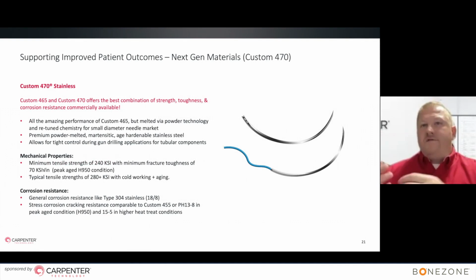So we talked about 465, and many of you may not be aware that there's a sub-variant of this alloy called Custom 470. This alloy provides very similar characteristics. It's a standard blend of Custom 465, but it maximizes toughness, minimizes grain size, and enhances machinability by providing this product in a powder-born process. So in other words, this is born as a powder and we consolidate that into the wrought form. We did tweak the chemistry slightly, and we produced that product through the powder melt technology, as I mentioned, and then we hot roll that product into a wrought bar product for the similar applications that you work with.